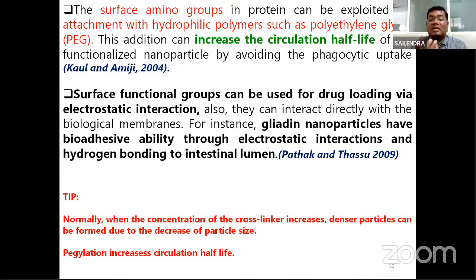So this surface charge is very, very important for electrostatic interaction between a protein nanoparticle and a drug molecule. If you have opposite electrostatic charges, definitely there is going to be interaction. And this particular interaction is used particularly in the intestinal lumen when you are targeting regions, particularly for irritable bowel syndrome, where you target the intestinal lumen in the colonic region.